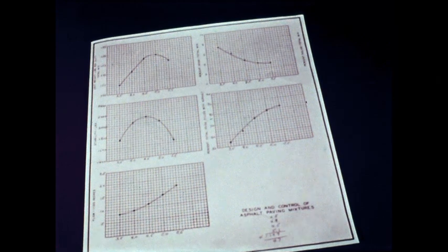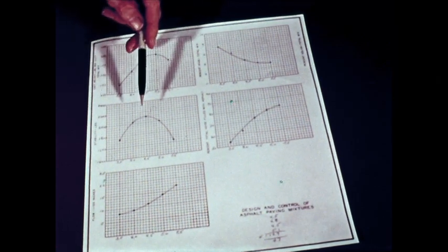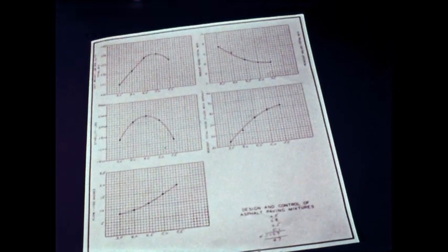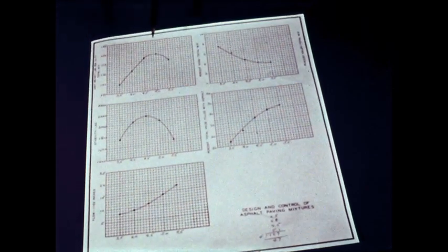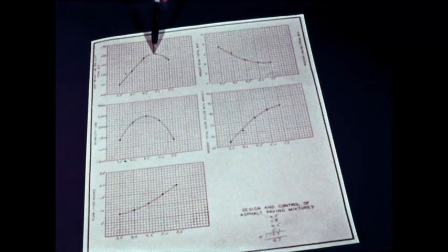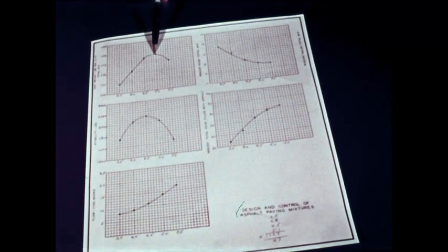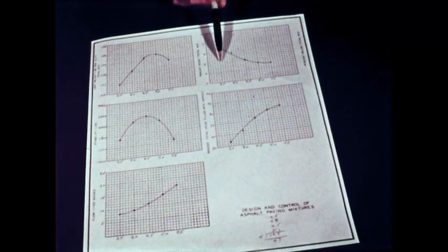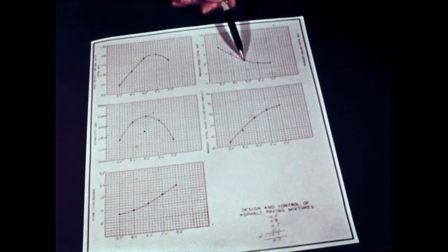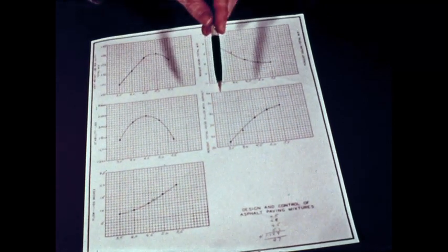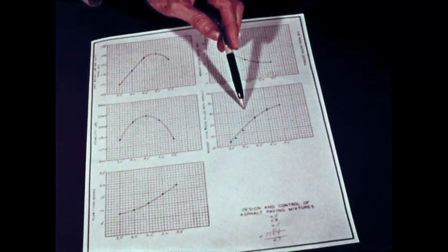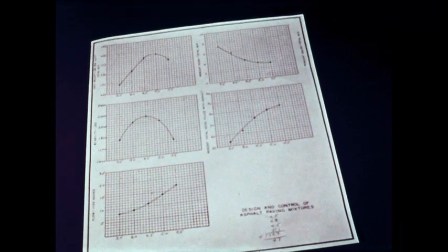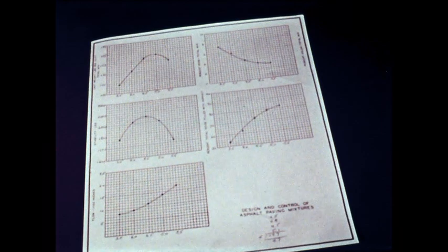on appropriate charts. The optimum asphalt content for the mix is then established by averaging the asphalt content at which maximum Marshall stability occurs, the asphalt content at which maximum density of the compacted specimens occurs, the asphalt content at which there is a specified percent of air voids, and the asphalt content at which a specified percent of voids in the compacted aggregate structure are filled with asphalt. Specified percentages mentioned in these last two items will vary, depending upon conditions for which the mix is being designed.